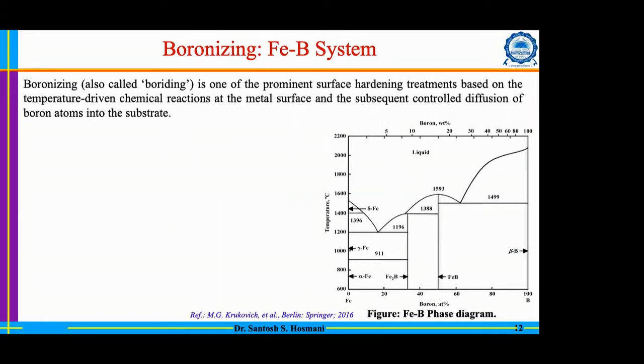However, there is a possibility of formation of iron borides, and two types of iron borides are generally formed: one is FeB and the other is Fe2B. From the composition and stoichiometry, you must have guessed that the FeB layer will form at the top, and subsequently the Fe2B layer will be there, and then you have the non-boronized core.